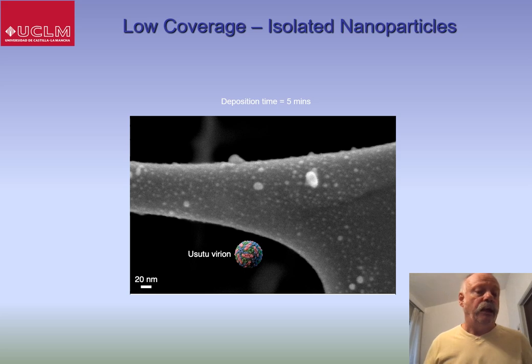Again, looking at even higher resolution, this time these are TEM images of silver nanoparticles coated onto a lacy carbon TEM grid, this time with a very low deposition rate. Very low deposition time, 5 minutes, to be sure that you can see the individual nanoparticles. And there they are, the 4 nanometer particles are here. And just as an example, this is an image of a Usutu virus, one of the viruses that we used in the study, to scale.